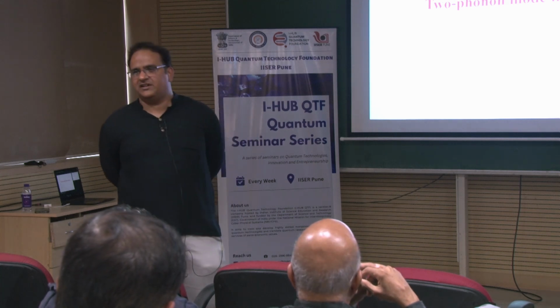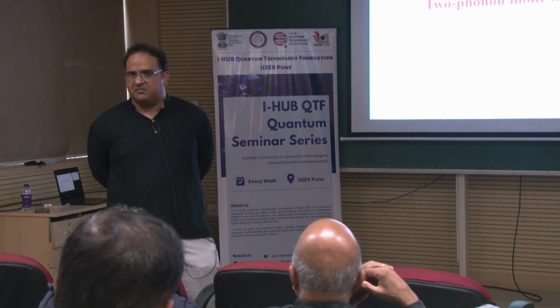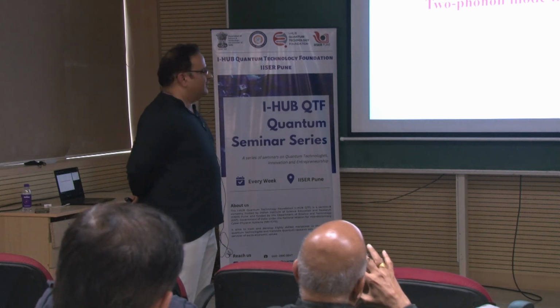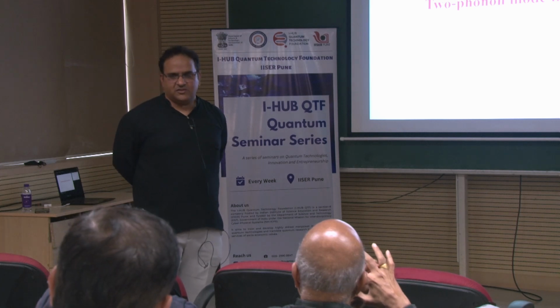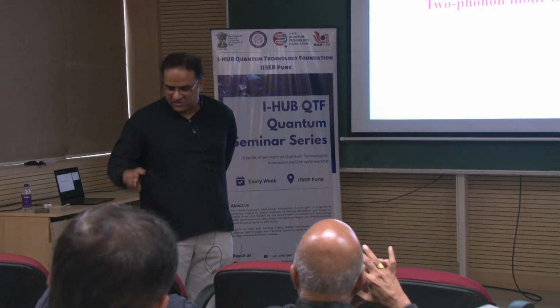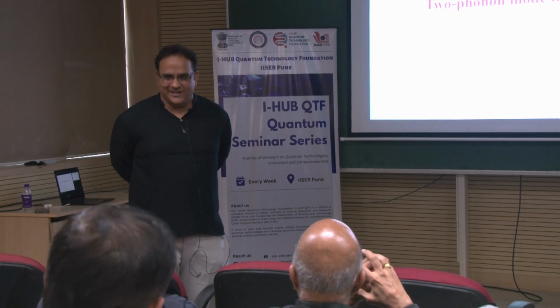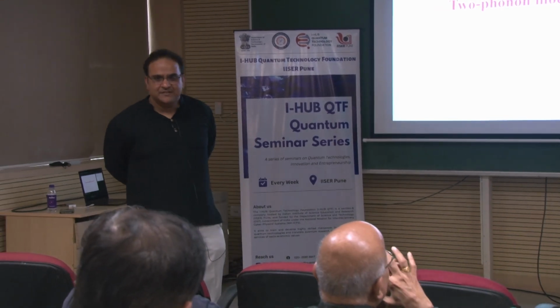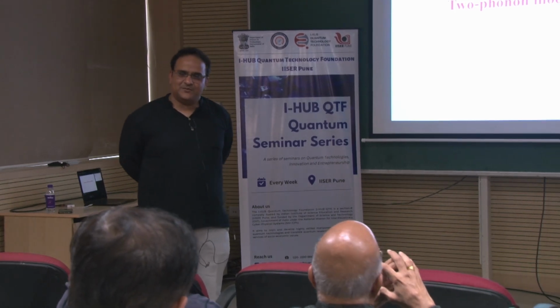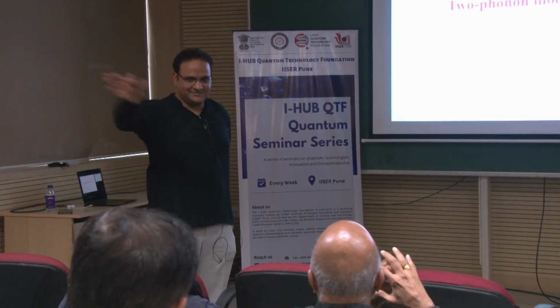Yes. At low temperature it is an extremely serious issue, because at room temperature the laser power may be 10%. Another problem is that the samples are poor thermal conductors because of the van der Waals gap. So anything you locally heat can take the tellurium, selenium or sulfur out, and it happened to GdTe3. So we heated it up to 200 degrees centigrade, and you see just tellurium, that's all.